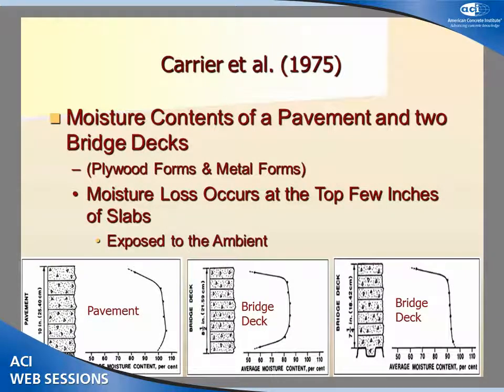In 1975, Carrier and his group studied moisture content of a 10-inch pavement and 2 bridge decks. One of the bridge decks was formed on plywood forms, which were removed after curing the concrete, and one of the bridge decks was formed on metal forms, which stayed in place. So you can see his result based on the first one.